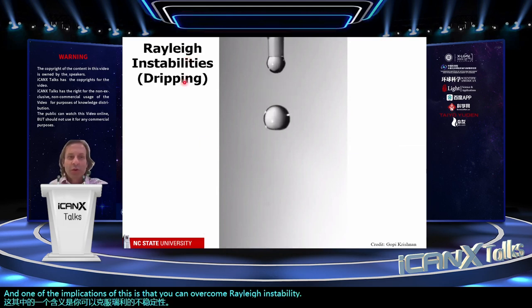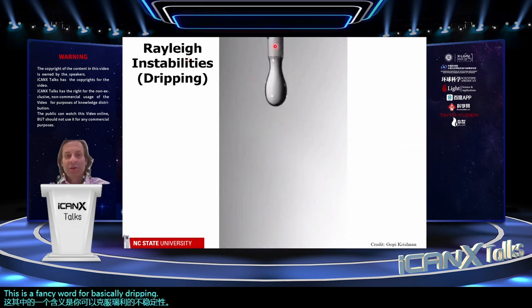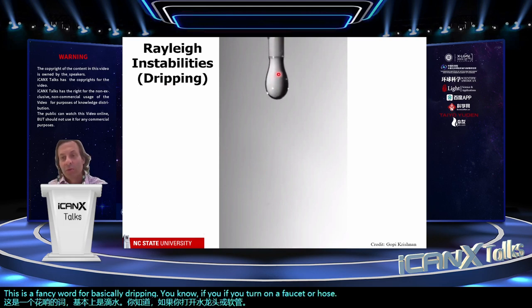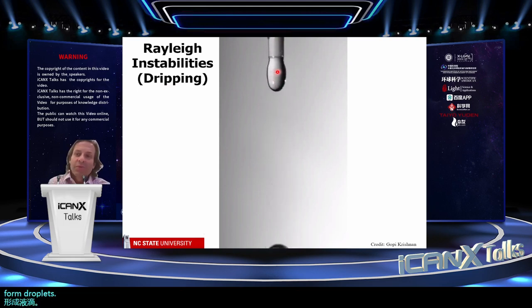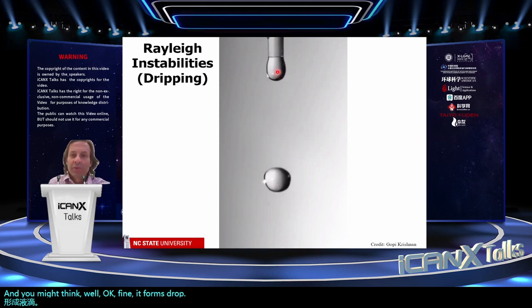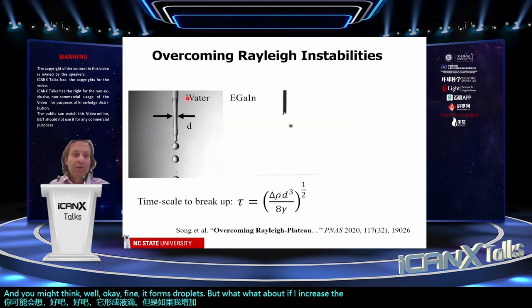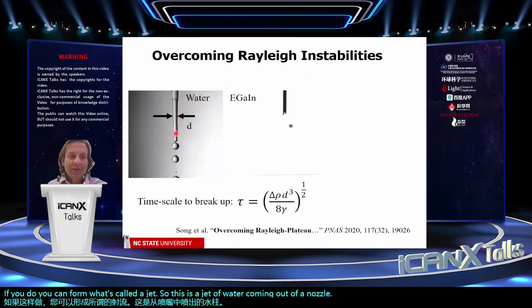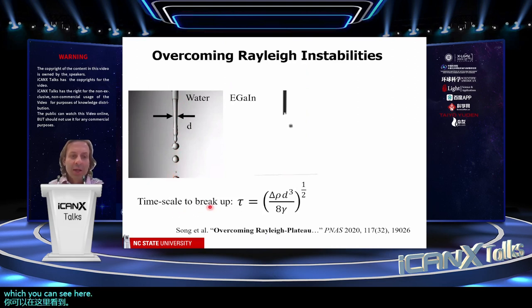And one of the implications of this is that you can overcome Rayleigh instabilities. This is a fancy word for basically dripping. You know, if you turn on a faucet or hose, you will form droplets. And you might think, well, okay, fine, it forms droplets, but what about if I increase the flow rate? And if you do, you can form what's called a jet. So this is a jet of water coming out of a nozzle, but still you're going to form droplets, which you can see here. Now, the time that it takes for droplets to form is a function of the diameter of your nozzle. So the smaller the nozzle, the less time it takes, and the larger your surface tension, the less time it takes.